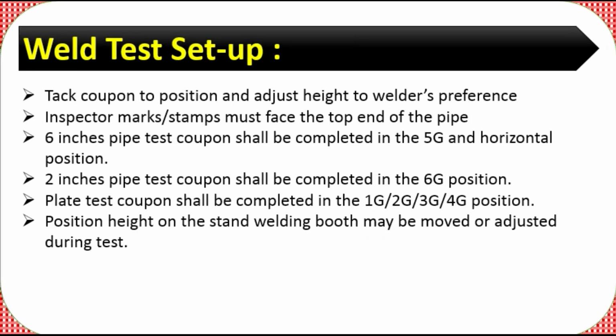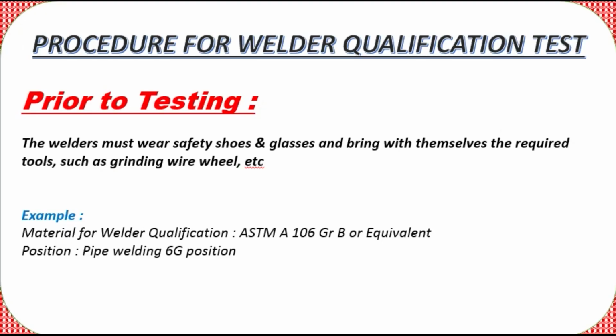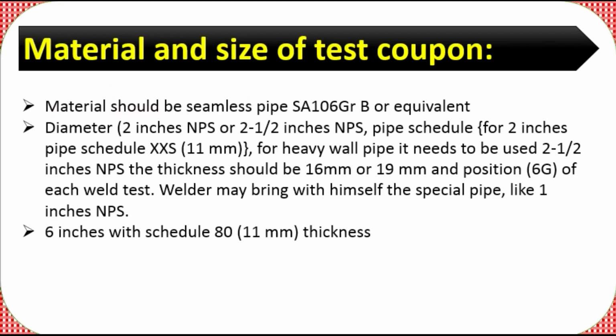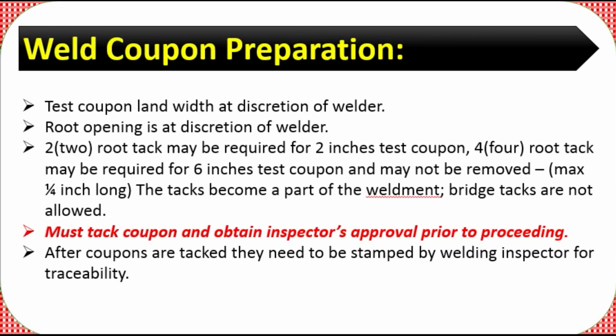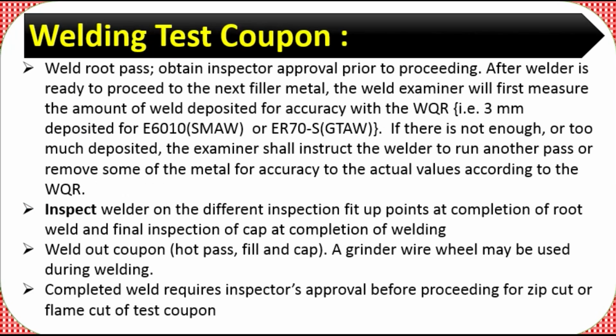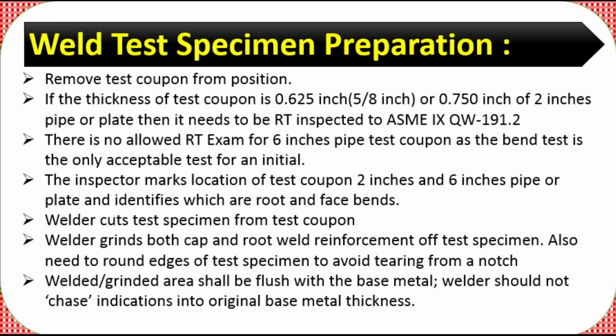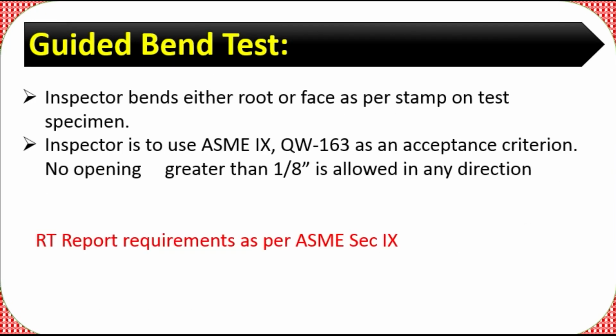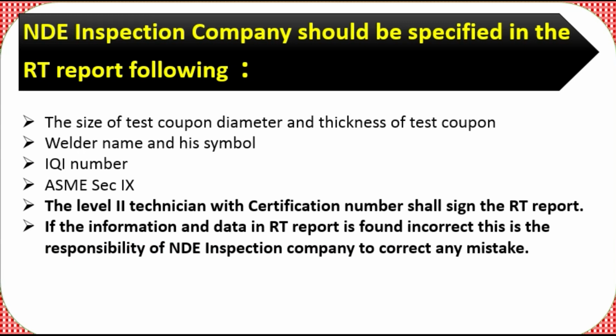So I think you understand from the beginning. Prior to testing, material and size of the test coupon, weld coupon preparation, weld test setup, welding the test coupon, weld test specimen preparation, guide bend test, and NDE inspection company specified in the RT report. These are the full steps when you are doing any welder test at site or in any fabrication shop. It is a basic requirement for any welder qualification test.